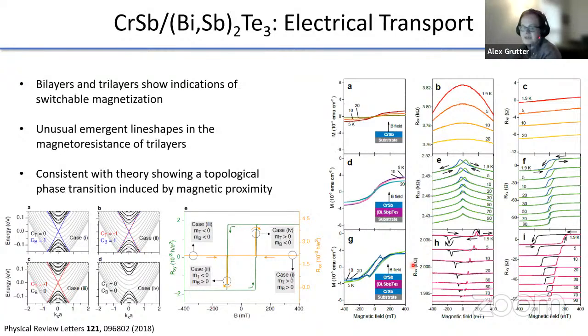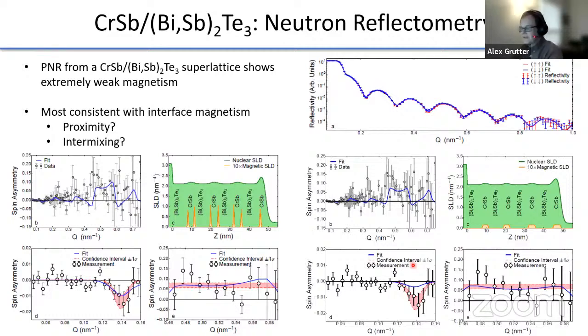So of course, what we want to do is then bring in polarized neutron reflectometry to understand whether this is a real proximity effect, and what you see is a ridiculously tiny signal. This is the best we could do after about 5 days. So we measure. At this region right here, you see maybe a really small bump in the spin asymmetry. All the way out here, you maybe see another small bump in the spin asymmetry. And the best fit is to a sort of interface moment related to a magnetic proximity effect.